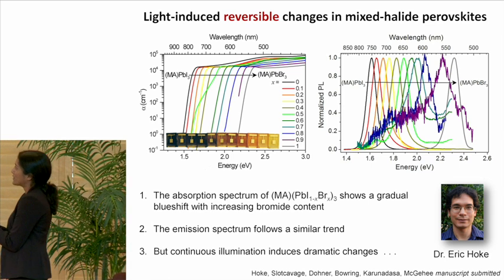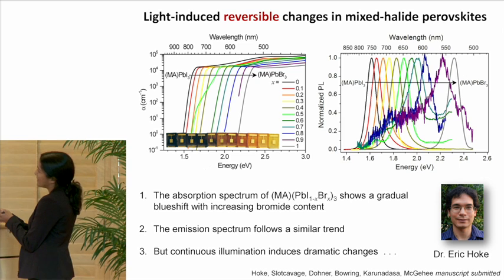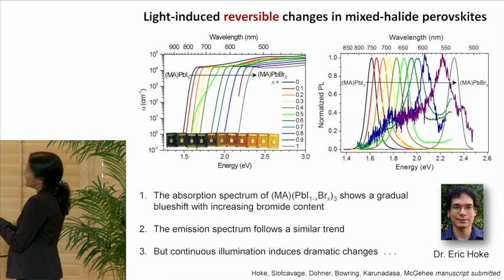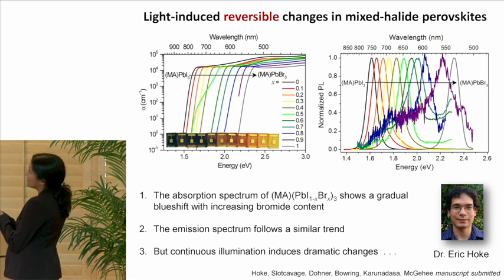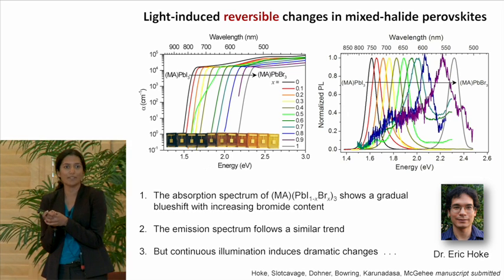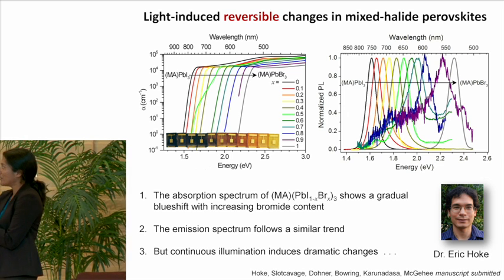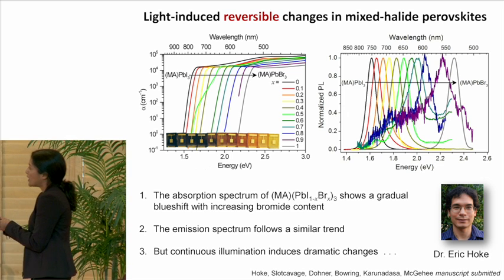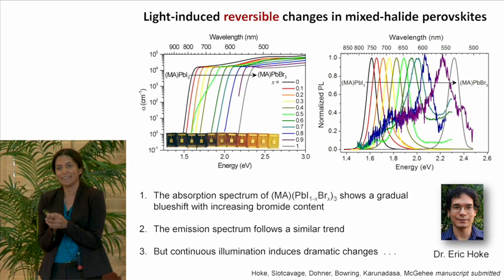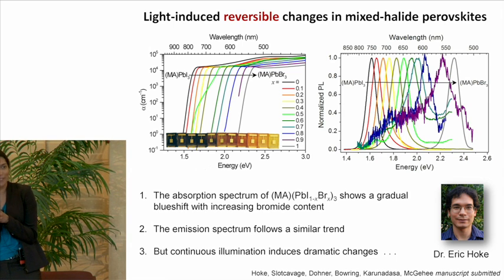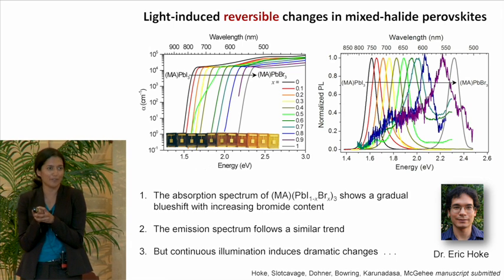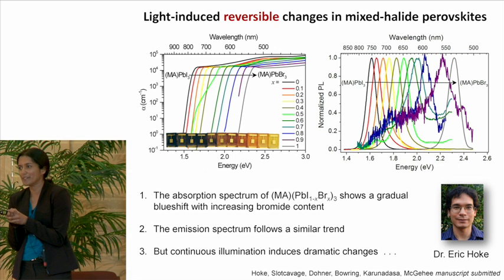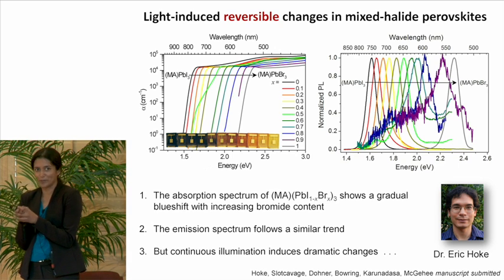lattice. And if we look at the photoluminescence spectrum of these materials, again, as we expect, we see that the energy of the emission goes to higher energies as we have more bromide in the material. This is exactly as we would expect, and we get this beautiful series. But Eric found that if he kept shining the light on these materials just at one sun illumination for just about a minute, this material changes dramatically.